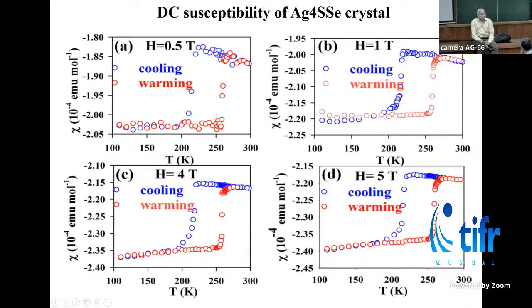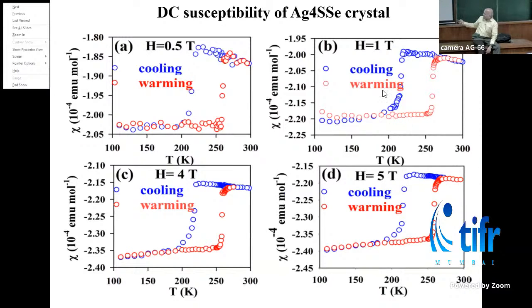The ionic conductors are generally, when you cool down, they become insulating. But there are cases where, through peculiar structural transitions, they can become a metal. It becomes a semiconductor and then becomes a metal. So I feel this offers a lot of playground to look at. We couldn't get superconductivity in this material. It shows large diamagnetism, and large diamagnetism is an indication that there is a change in the Fermi surface. So it started as a superionic conductor, went to a semiconductor, becomes a metal, a dirty metal,